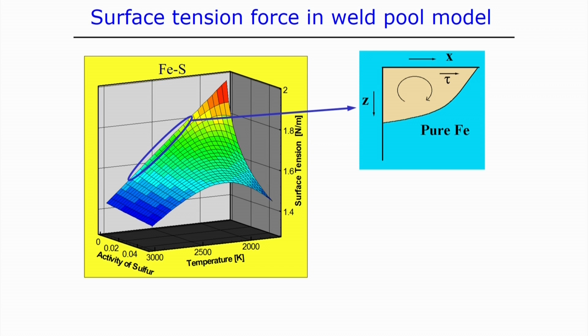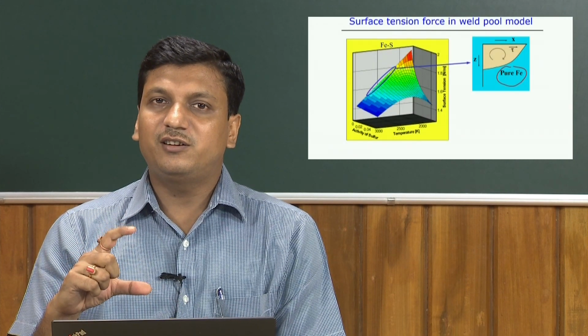So, in this case we try to represent the nature of the Marangoni convection in the weld pool. It is the case of pure iron, that means there are no surface active elements, showing the depth direction and, on the top surface, the weld pool width. Here the shear stress is basically acting from the center to the outward periphery. That tries to drive the molten material from the center to the outward periphery, and we can say it creates material flow in a clockwise direction on this plane. This nature of material flow tries to increase the width of the molten pool and decrease the penetration of the molten pool.